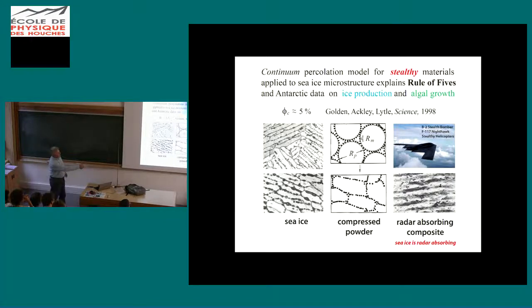Basically, if you had just little individual metal particles disconnected in an insulating host, you wouldn't have much conductivity. But when they connect up, when they form electrical pathways, that's what changes everything, and that's what the percolation threshold is. You see all kinds of interesting behavior in, say, the complex permittivity or the conductivity of such a material.